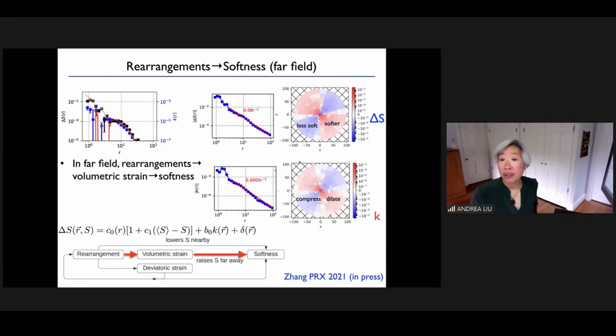Okay. So, the volumetric strain is giving you a dipolar pattern, which is compressing the particles here, that makes them less soft, and dilating the system there, that makes them more soft, okay? And in fact, that gives us this piece here of this equation where the change of softness has this piece that's proportional to the volumetric strain, okay? And those are these arrows here.